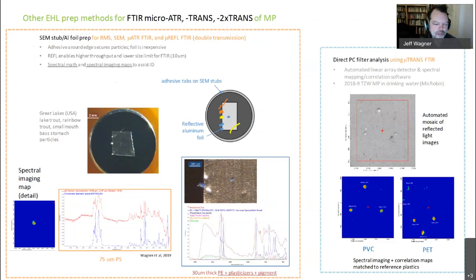So on the left, you see a prep method in which we take the typical SEM stub with adhesive carbon tab, which we use for a lot of our analyses. But in this case, we have an inexpensive aluminum foil square mounted on it, which we have found suitable for getting decent signal to noise back to the FTIR detector. By mounting particles and especially fibers along the edges of the foil, we can secure the particle in place, but also have a portion of it over the reflective surface. And this has enabled slightly higher throughput as compared to ATR and lower size limit down to about 10 microns, especially for fibers.